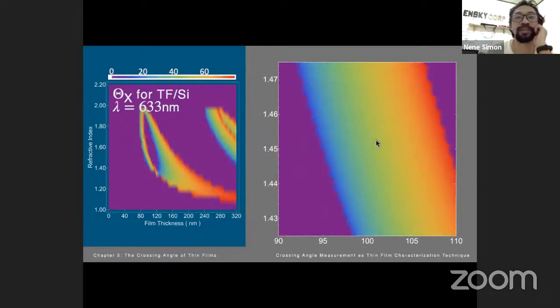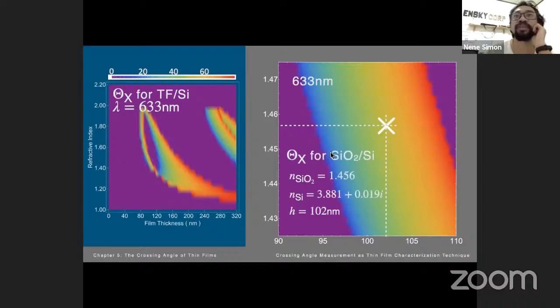So to zoom in, we have here the parameters for silicon dioxide on silicon. So for 633 nanometer incident wavelength, the refractive index of the oxide is 1.456. The substrate is 3.881 plus 0.019i. And again, here the thickness, I'm assuming the thickness 102 nanometers. The corresponding parameters are shown by these dash lines, and the cross mark shows you the position of the crossing angle. So the color there represents the value of the crossing angle.